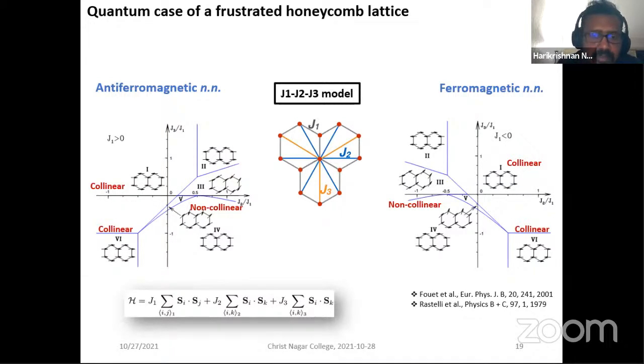If you focus on one of the phase diagrams, either ferromagnetic or antiferromagnetic, it tells you what type of arrangements of spins on the honeycomb can happen if you change the energy values of J1, J2, and J3. If you tune these energies, all the spins can point in one way, or some of them can point as spirals, or they can be antiferromagnetic, things like that. J1, J2, J3 are all energies, a certain amount of electron volts, or a few kelvins for that matter. So if you change those, how do the spins arrange? What kind of arrangement do you get? That's what this diagram tells you.